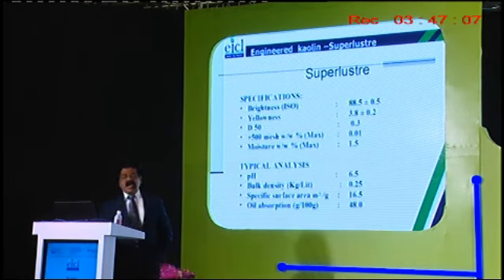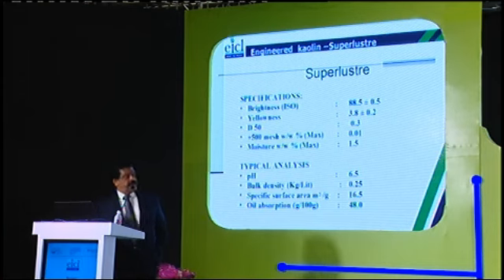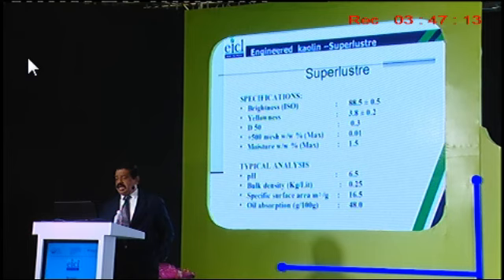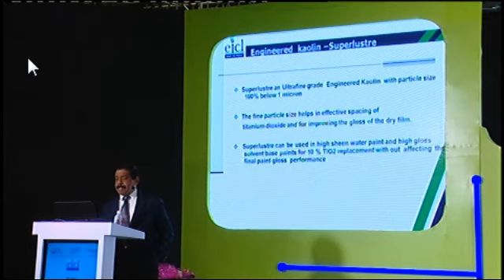Next is an engineered kaolin product of ours, the grade Superluster. You can see the D50 is around 0.3 and it has a brightness of 88. This is an ultra-fine engineered kaolin with 100% of particles below 1 micron. The fine particle size effectively spaces titanium dioxide, improving gloss and dry film properties. Superluster can be used for high sheen water-based paints and high gloss solvent-based paints for about 10% replacement of titanium dioxide without affecting the final paint performance.